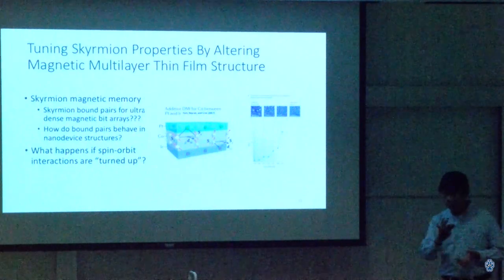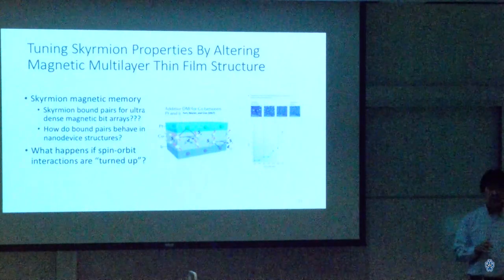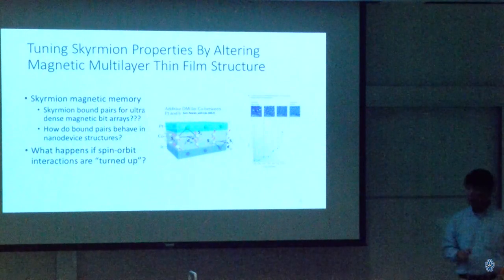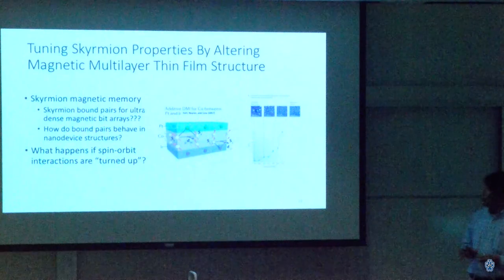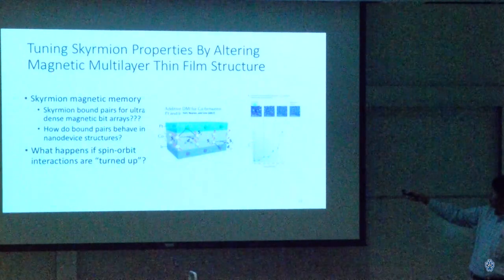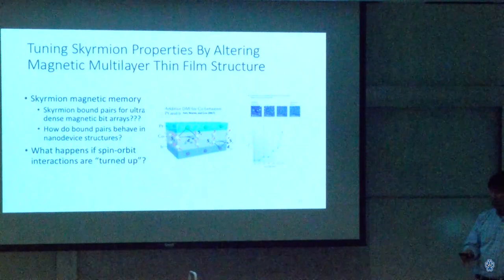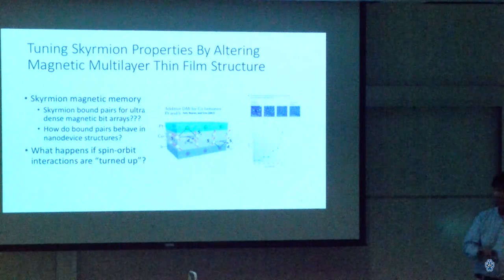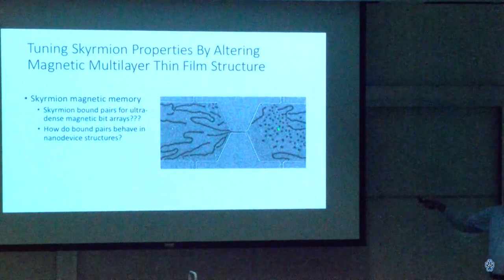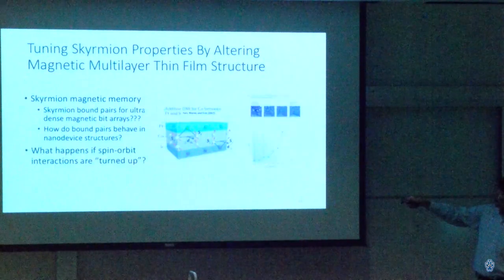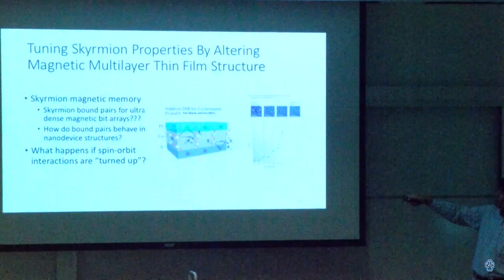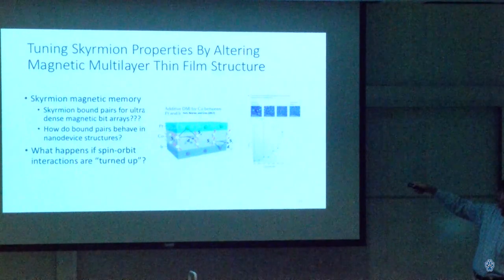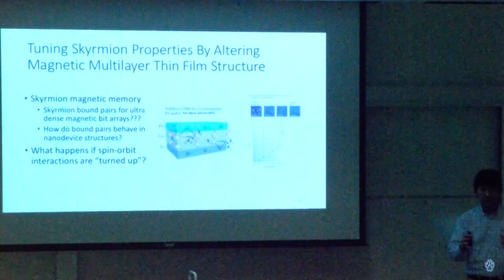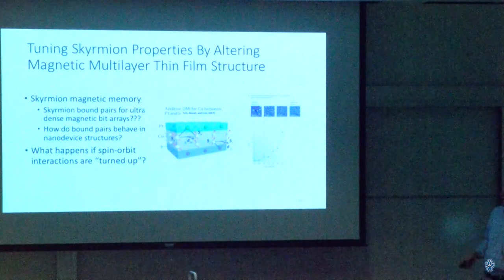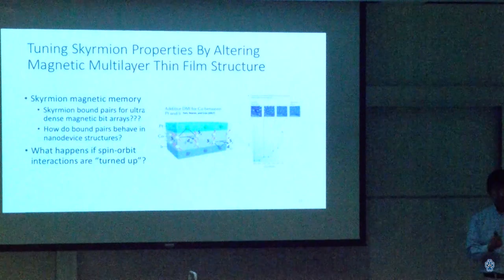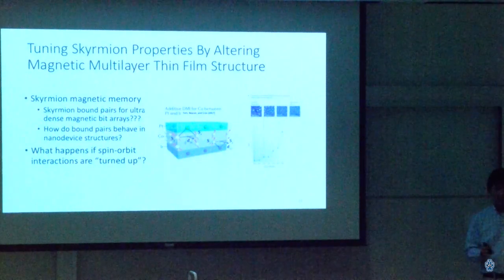So the result is that by changing the basic properties of materials, by manipulating the spin exchange as well as the spin orbit exchange strength, you can get various different types of skyrmion patterns to form. As I showed in the case of a magnetic thin film multilayer, or in this nanostructure, and by chemically changing the multilayers or structures by adding, say, platinum and iridium, you can go from having a very dilute state in which skyrmions are very widely spaced apart to having them densely form. So just by twiddling the parameters for materials, you can get skyrmions to appear in various different ways.